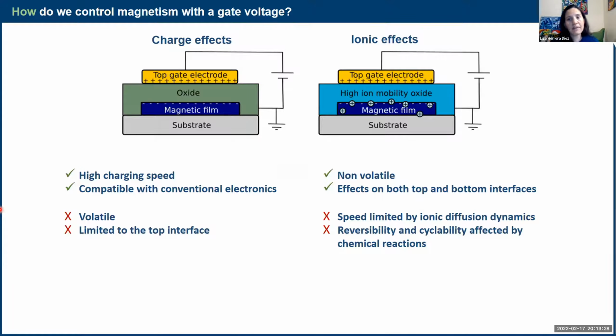On the other hand, you have ionic effects. So the structure of the device could look pretty much the same as the one in the charge effect. So your magnetic film, an oxide, a top electrode. Only that you want to pick an oxide that has high ion mobility. So here, when you apply your voltage, you're actually generating an electric field, and you're not so much interested in the charges that you're going to accumulate in your magnetic film, because of course that's going to happen anyway. You're interested in using this electric field to move the ions in the oxide.